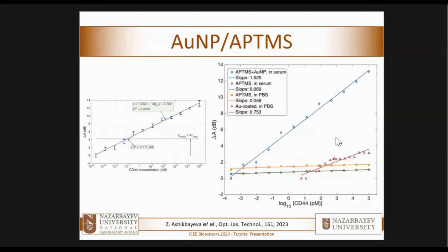What is quite interesting also is that we try to play on the functionalization to see if we can make the detection better. And while these two curves right here are the previous curves that I've shown before, these two additional curves show a device made in this case with metallic thin films rather than the APTMS functionalization.